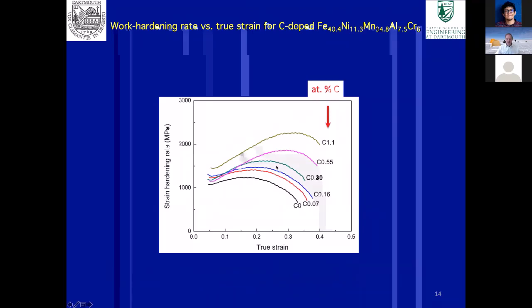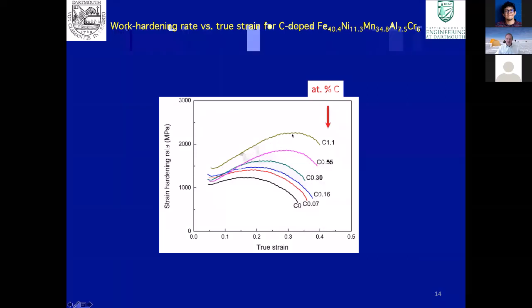Once you add carbon to the material, 2 things happen. The work hardening rate increases more, and you continue work hardening up to a greater strain as well. By the time you put in 1.1 atomic percent carbon, you see a much greater work hardening rate, and work hardening continues to over 30% strain.